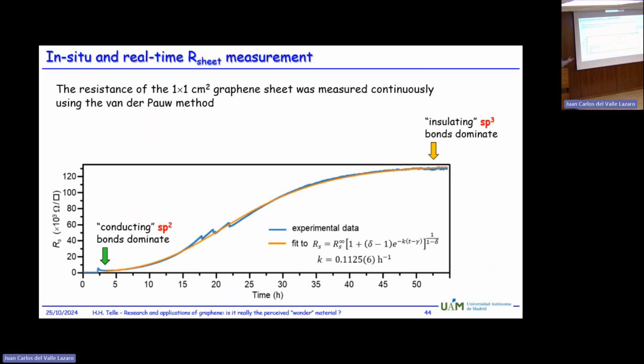So basically, as I said, during the actual tritiation process, we were not able, like in the one experiment I have shown with hydrogen, to continuously monitor with Raman spectroscopy, because this chamber had no access for optical measurements. So we had to rely on resistance measurement. And here is actually the example. We start more or less at 0. So it's completely conducting, and then with time, more and more tritium is absorbed until it saturates, that all possible bonds are occupied, and then you have a saturated signal where you have changed from sp2 configuration to an sp3 configuration.